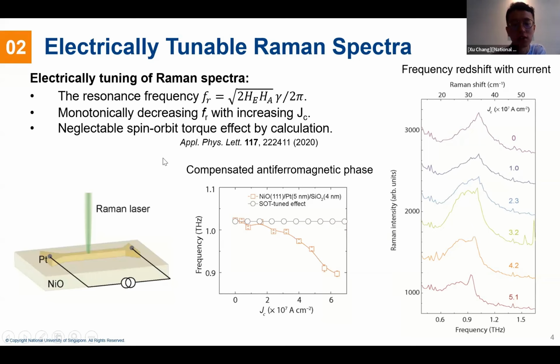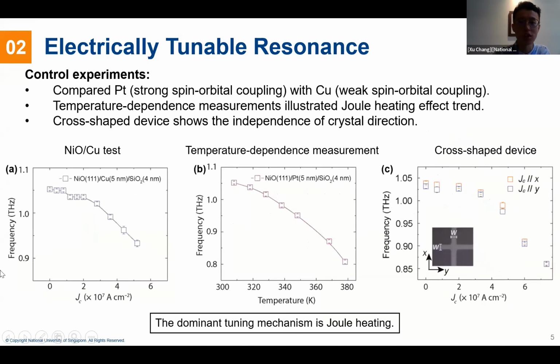We have calculated the spin-orbit torque effect with some reference methodology. The calculated SOT effect seems not dominating in our experiment, and can be seen as negligible. But calculation is just calculation. We have also done some control experiments to illustrate the dominating mechanism. We first compare the platinum device, which was shown before, with a copper device.